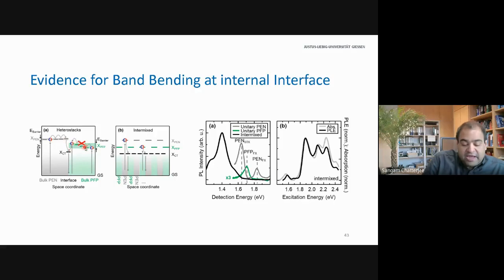In the PFP, on the other hand, we have coupling effects, and the interface to the pentacene leads to these coupling effects producing something like a band gap bowing, and it takes 3 to 4 molecules for the energy levels to actually reach the bulk state, and then it doesn't matter what happens on the side. But you actually get a bowing of the potential towards the interface. This is something which is not very surprising for inorganic semiconductor people, because there is a band gap bowing at virtually every interface. That's the nature of the PN junction. And it also happens in these molecular systems because you have the coupling between the molecules.